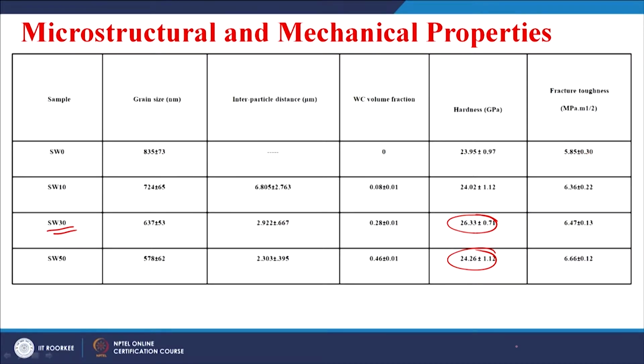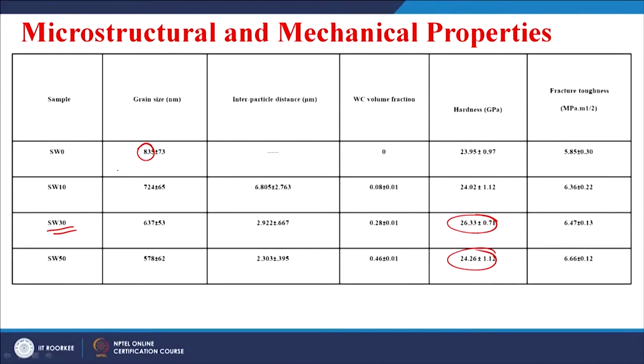whereas fracture toughness improves from 5.85 MPa root meter to around 6.67 MPa root meter. If you look at the correlation between the microstructural characteristics and the mechanical properties, the grain size decreased from 835 nanometers to 578 nanometers with increase in tungsten carbide content. The interparticle distance also decreased with larger amount of tungsten carbide in these composites. So, it indicates that while sintering, the grain growth was restricted by the presence of a larger amount of tungsten carbide